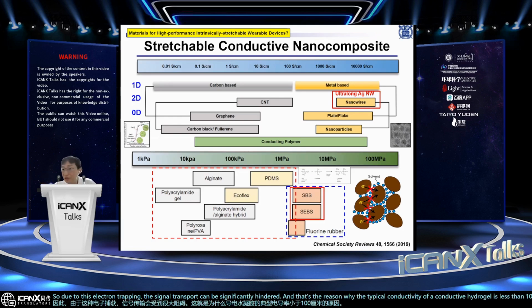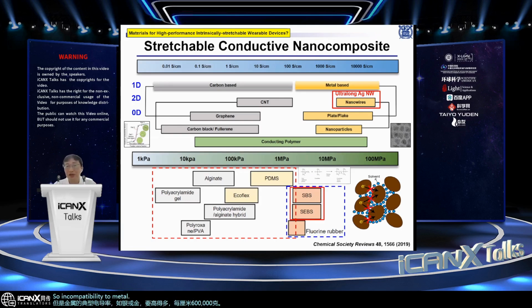But the typical conductivity of metal, like silver or gold, is much higher, 600,000 Siemens per centimeter. So in comparison to metal, the conductivity of the conductive hydrogel is too low to make an intrinsically stretchable wearable device. So in that case, we can think of another elastic material rather than hydrogel. We can think of elastomer, chemically cross-linked elastomer like PDMS or Ecoflex, or physically cross-linked polymer, thermoplastic elastomer like SBS.